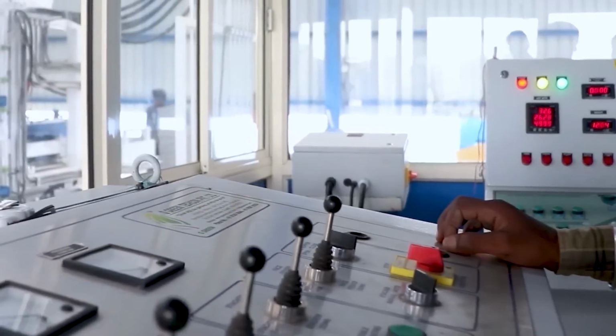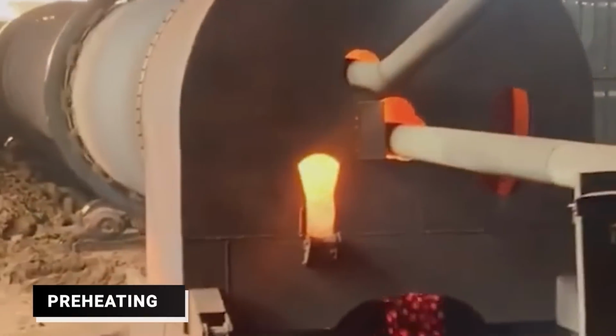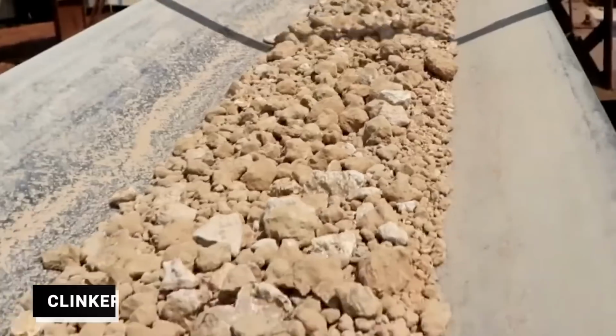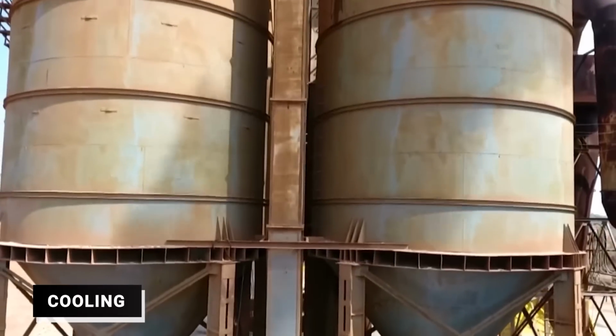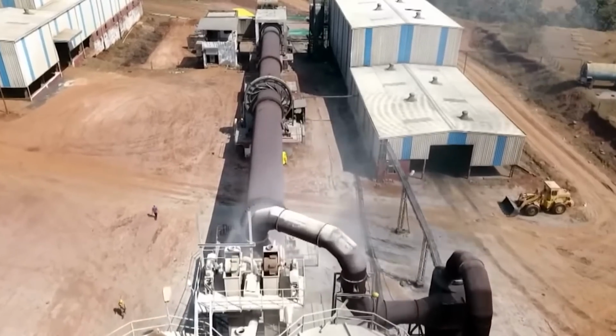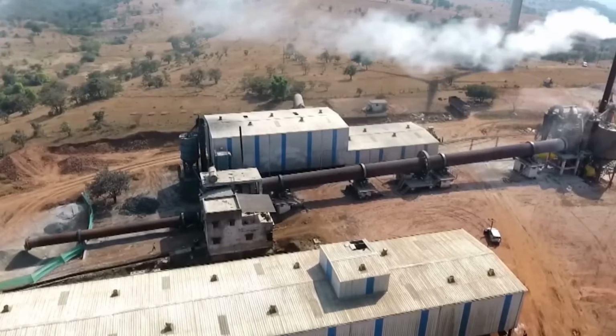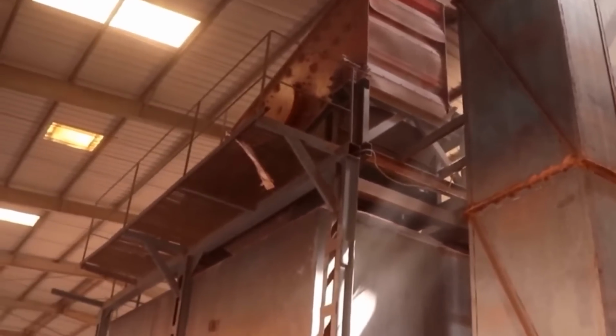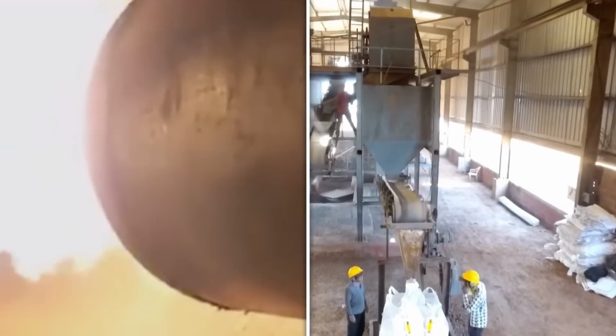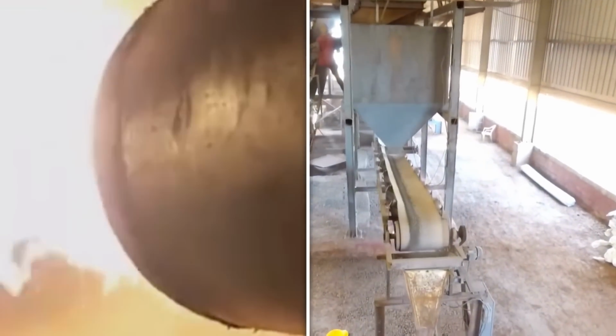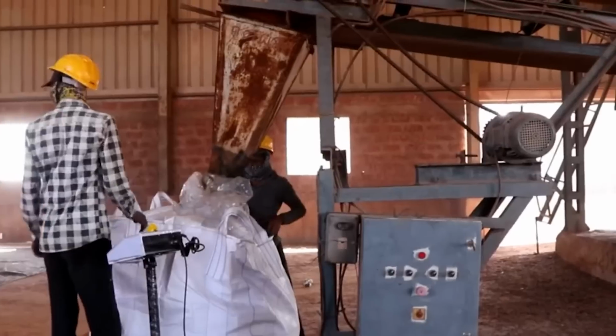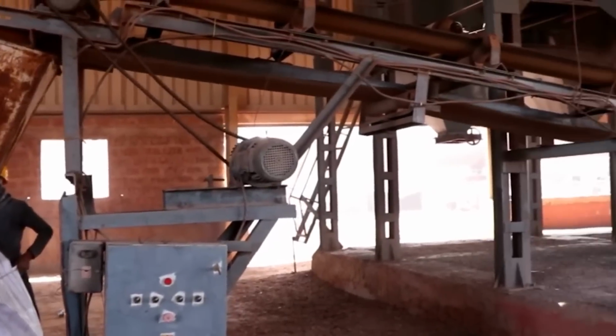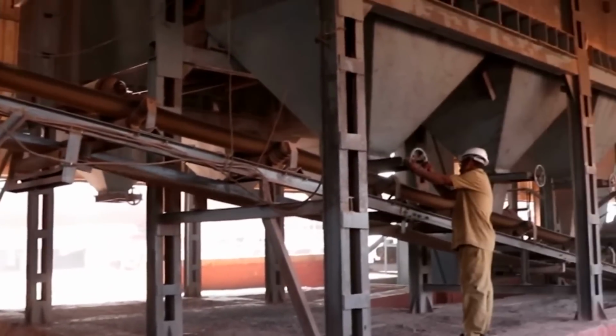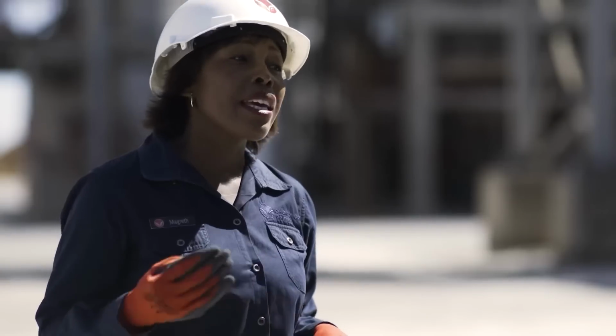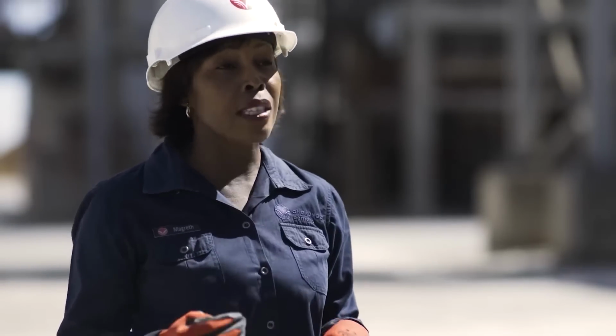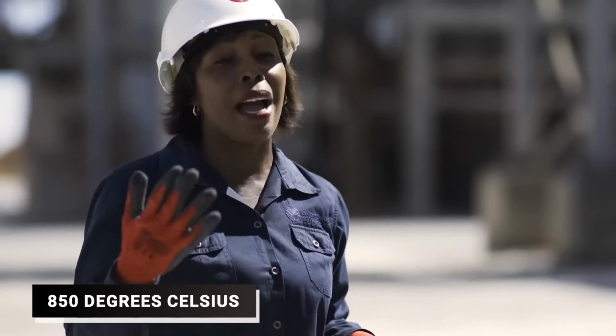The process involves several key stages: preheating, calcination, clinker formation, and cooling, each driven by complex chemical reactions and sophisticated machinery. The journey begins with the preheater, a critical piece of equipment where raw meal is initially subjected to preheating. Inside the preheater tower, raw meal is exposed to hot gases from either the kiln or cooler. This heat transfer raises the temperature of the raw meal to approximately 850 degrees Celsius.